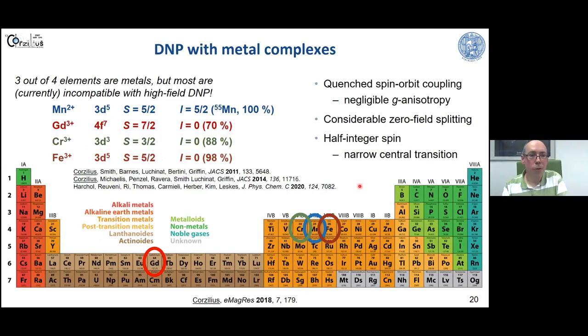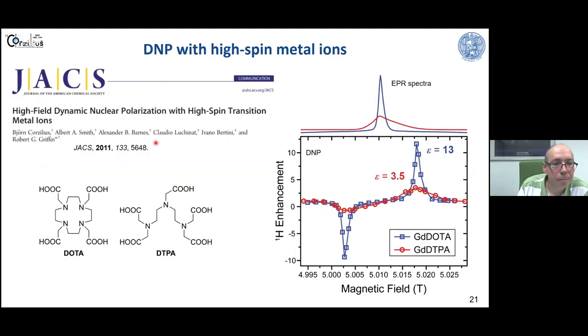Now coming back to these examples, I've shown you manganese, gadolinium, chromium, and iron. And these are all high spin metal ions with half-filled electronic subshells, or in the case of chromium, it's a half-filled t2g shell practically in a strong ligand field. And in this case, we can practically reduce our system, and this is the beauty of it, to a central transition, which is occurring mostly centered around the free electron g factor.